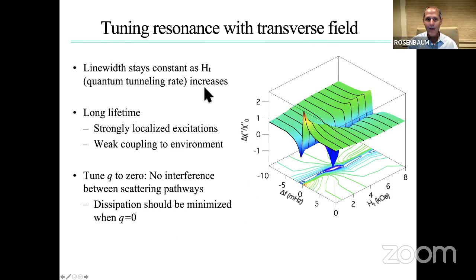Okay, so what have we found out in tuning this resonance with the transverse field in these isolated spin clusters? The line width stays constant as the quantum tunneling rate increases, so that's good. We can deconvolute thermal and quantum effects. I haven't shown you here, but it has a long lifetime. In fact, the quality factor, capital Q, and I'll show you that, is effectively independent of transverse field, and is of the order of 10 to the 5th. So it's the frequency we're driving these things at, which is say 100 hertz, versus the millihertz line width of this system.